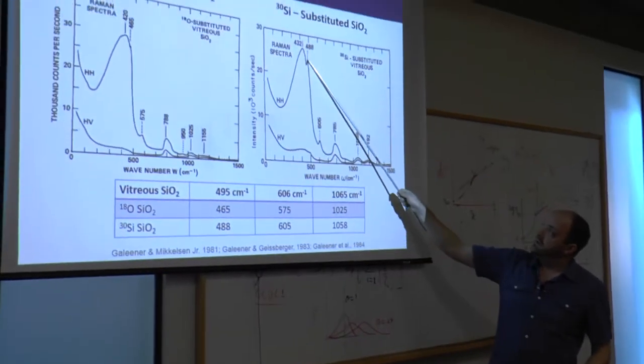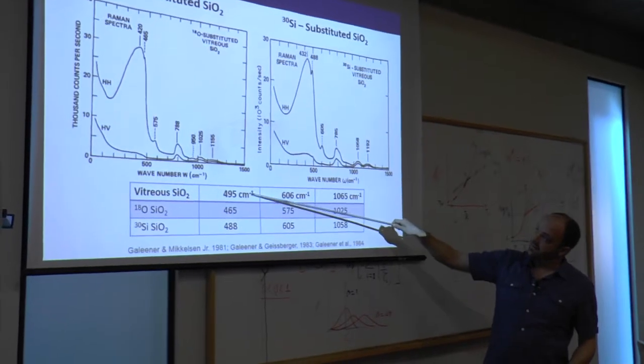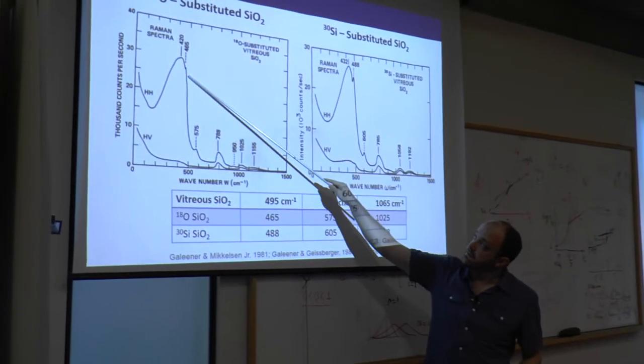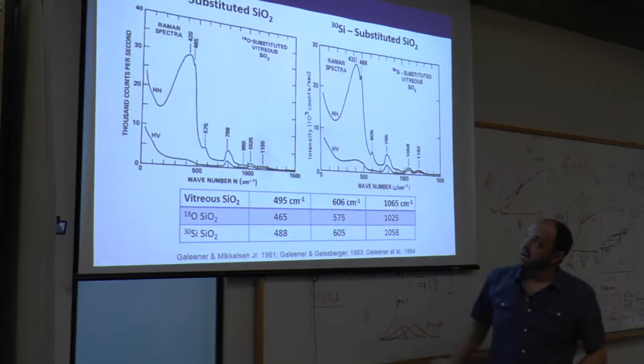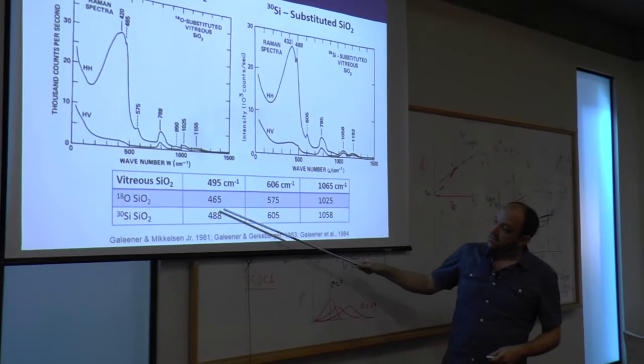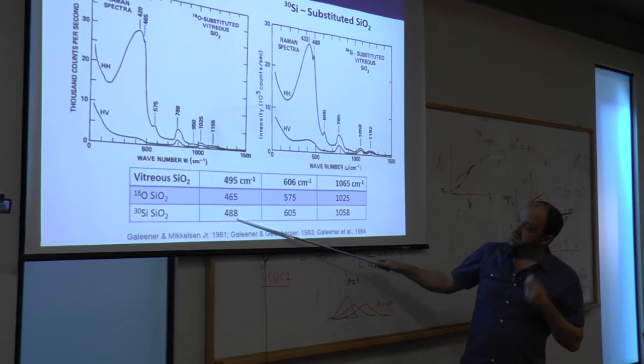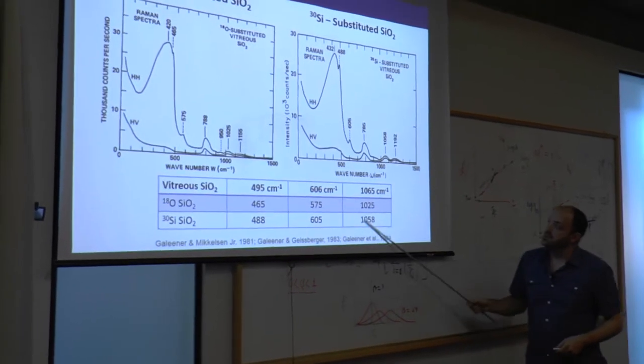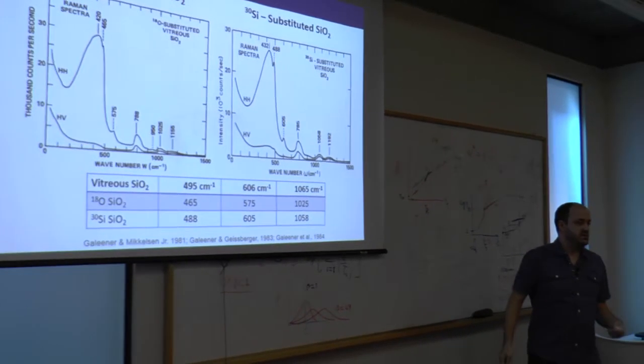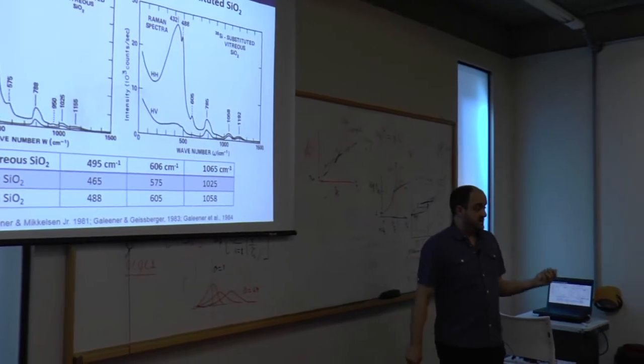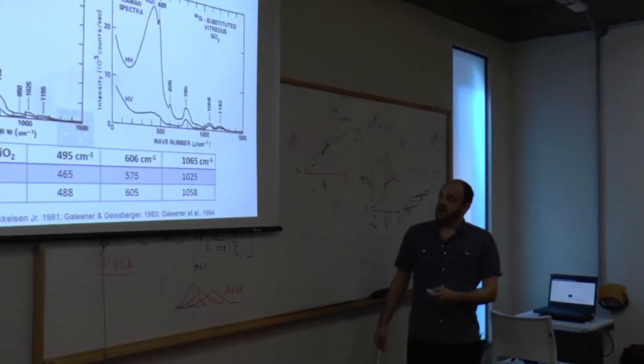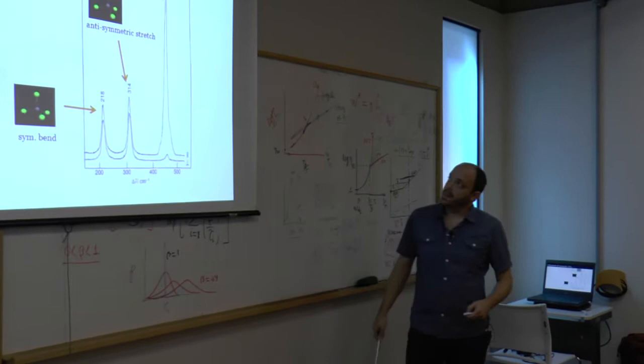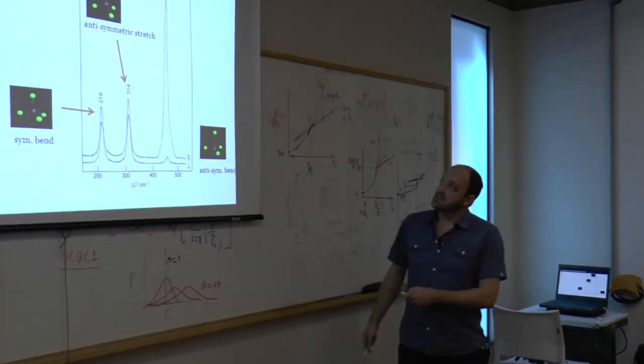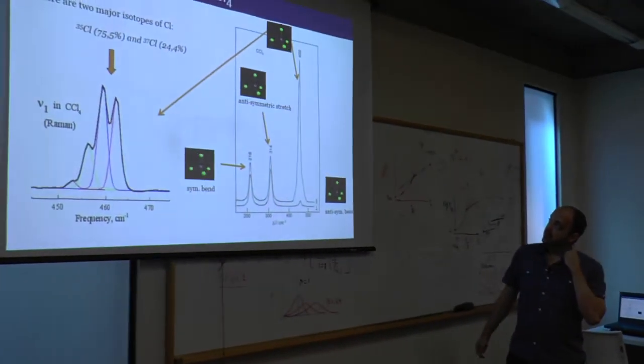So in pure silica, for example, the peak here is at 495. In the oxygen substituted spectra, it's at 465, and in the silicon spectra, it's at 488. You can see some other examples, but you see this isotopic shift. So this spectroscopy is really sensitive to the isotopes in the system. I think you may have seen this example already, but I'll go through it again.